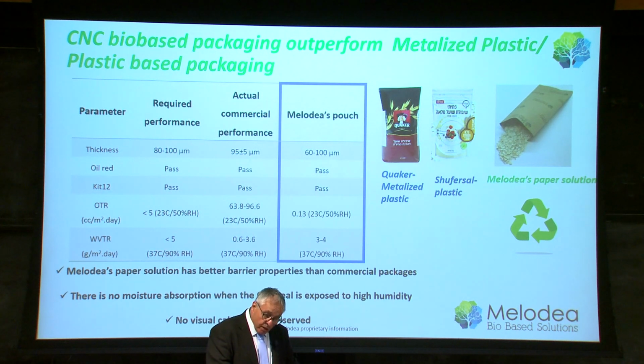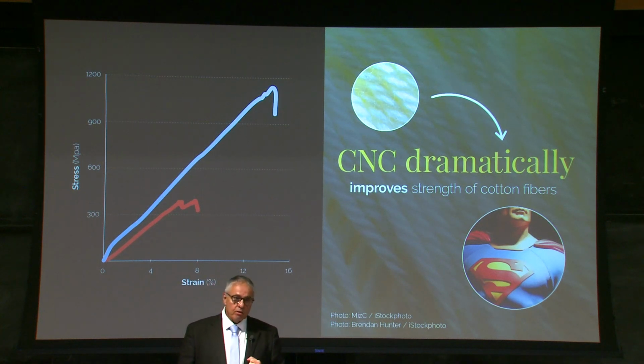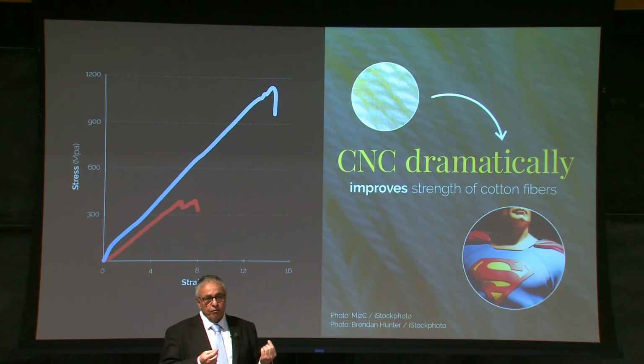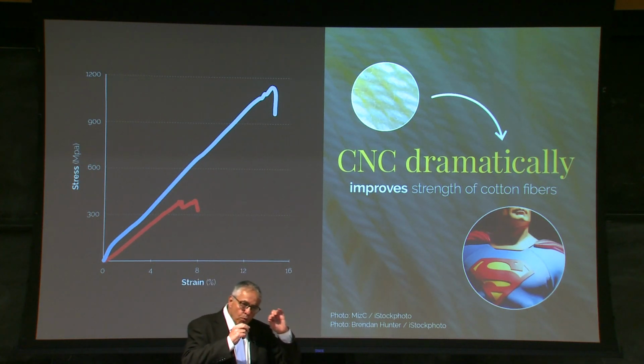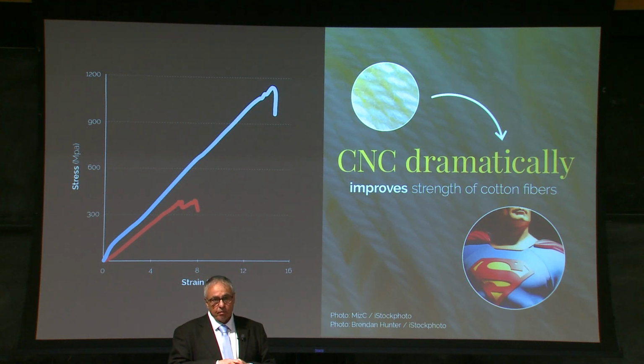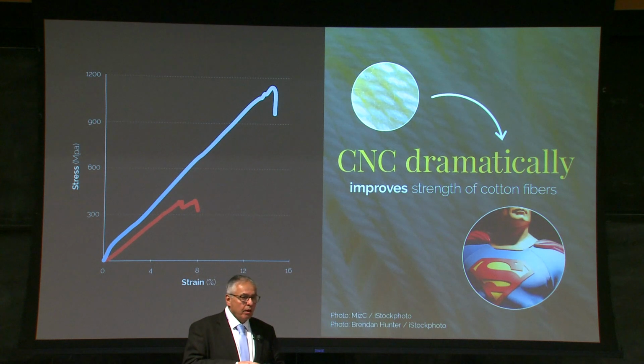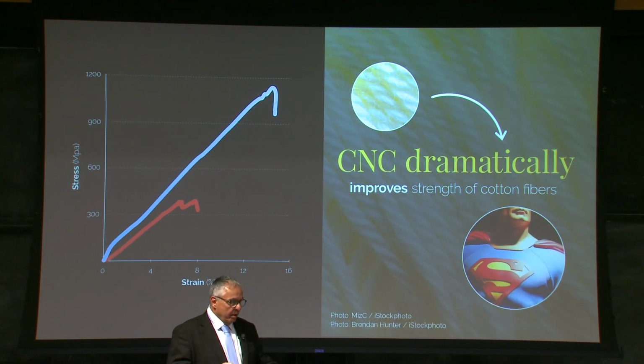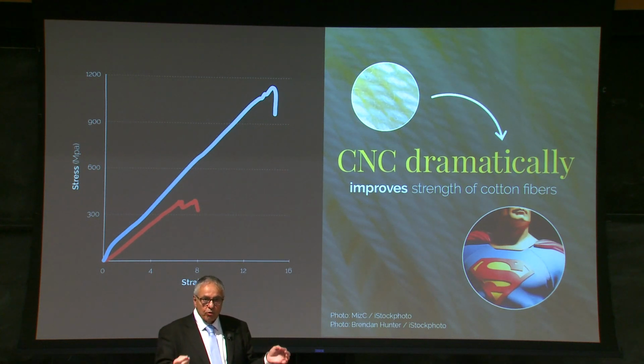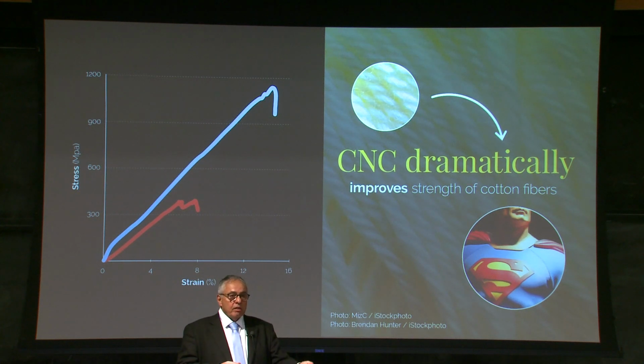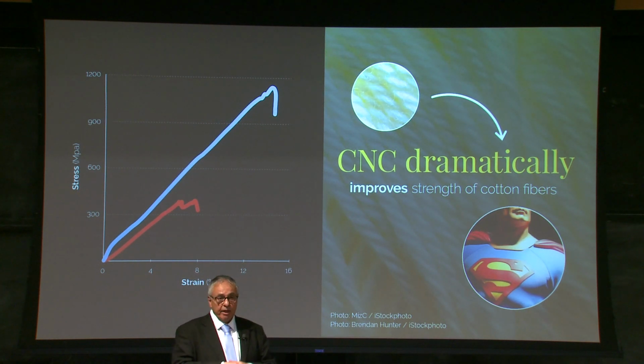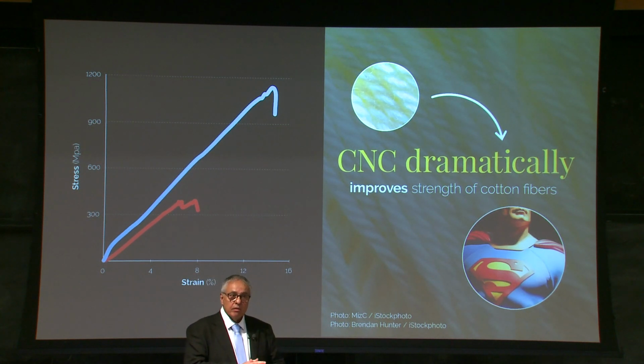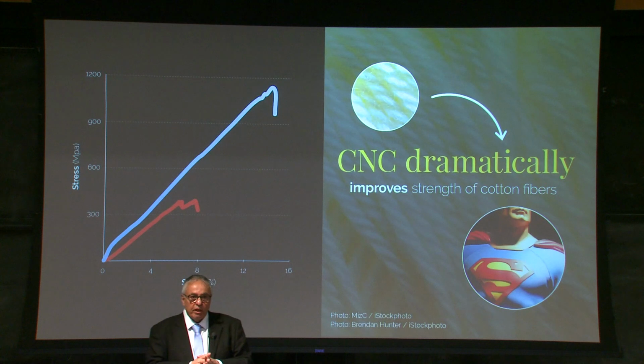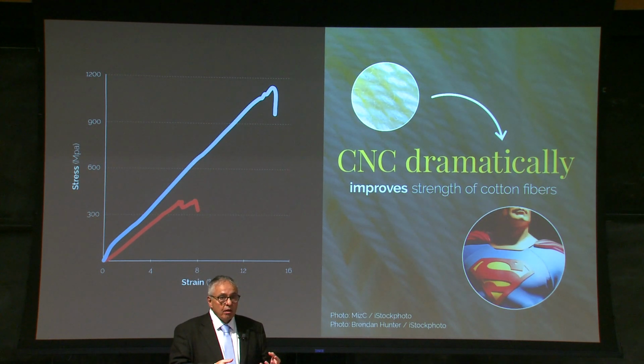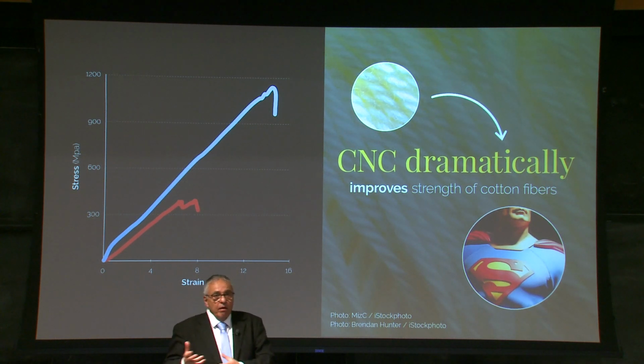What else you can do with the cellulose nanocrystals? To reinforce other materials. For example, we took cotton yarn, the same that my shirt is made of, and we coated it with just 1% by weight of cellulose nanocrystals. And as you can see from the Instron data, the red one is regular cotton yarn, whereas the blue one is the same one coated with the cellulose nanocrystals, added only 1% to the weight, and you can see there was increase in the modulus, increase in the strain at break, and of course, as expected, the toughness is close to 500% increase compared to the other. So what it means is that we can either make the same strength of shirt with 1/5 of the material, or make a much stronger shirt.